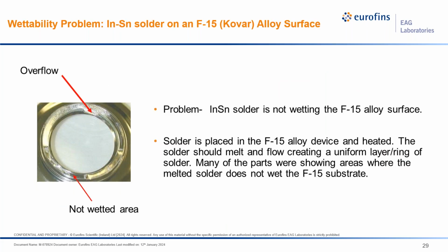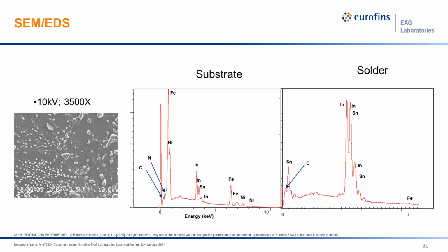So I'm going to jump right into some examples. This was a Kovar part that came in with a solderability issue. The substrate was not wetting, and in the optical image over here, you can see areas where the surface did not wet, areas where the solder overflowed onto the parts. And sample came in with a variety of possible scenarios as to what the problem was. Went into the SEM lab first, and nothing was really found. We see the Kovar peaks as expected, iron, nickel, a little bit of carbon and nitrogen. In the areas with the solder, we just see the indium and tin, also a little bit of carbon.